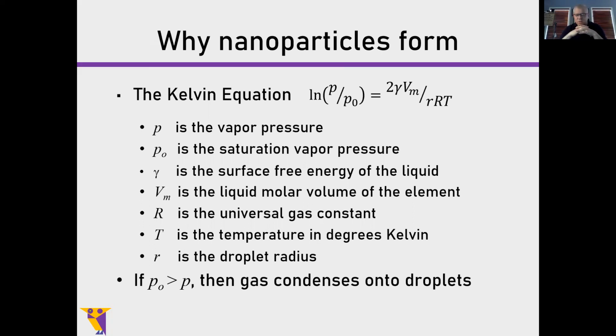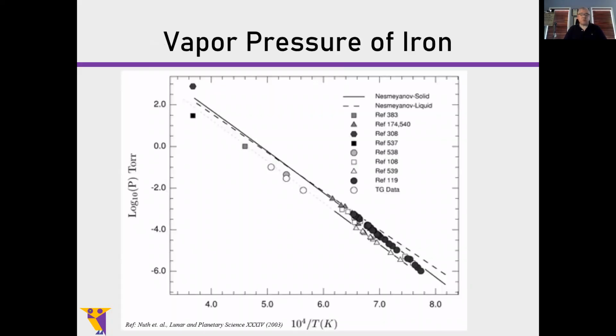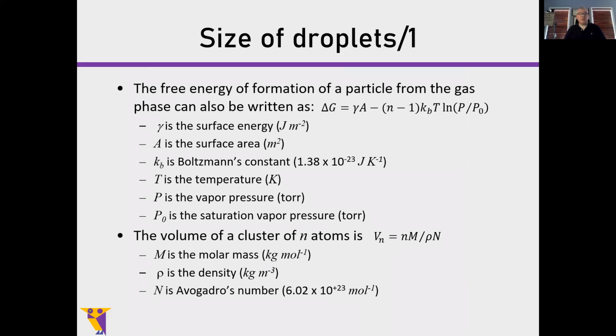And the answer is, like I said, you typically will shoot ferrocene or iron pentacarbonyl in. They will decompose, liberate free iron atoms, and then you expect these nanoparticles to form. Well, why and how? If we go back to classical thermo, if we look at the Kelvin equation for condensation of droplets, very simple, straightforward equation, wonderful. The vapor pressure of iron is well known. And even as a liquid, it has a vapor pressure. It's very, very small.